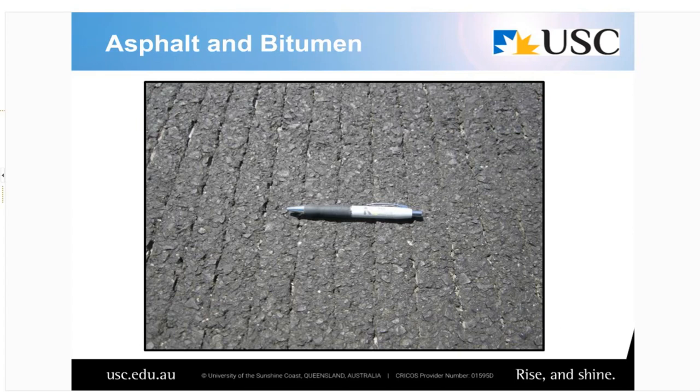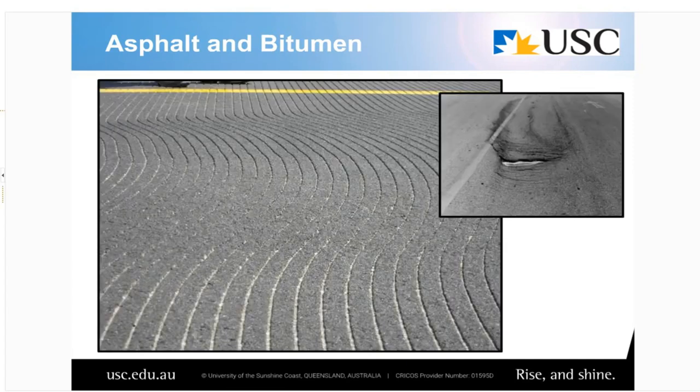These are just a couple of examples of those distresses, and again, if you've seen my presentations at the various AAA and other conferences, these won't be unfamiliar. Groove closure has required a couple of airports to resurface significant portions of their runways for no other reason than because their grooves were closed, and well ahead of schedule. Shearing in itself isn't necessarily a significant failure of the surface, but when it gets to the point that there starts to be a crack and then a tear at the back end of that area, then people do start to get a bit worried.